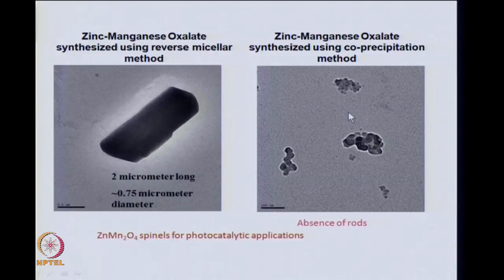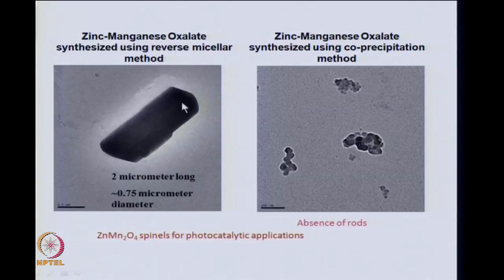On the right side, we have used the same conditions for making the same compound using the co-precipitation method, where we do not have any surfactants or microemulsion. And as you see, this microemulsion process containing a cationic surfactant gives a nanorod kind of morphology, whereas in this case, where we have not used any surfactants or microemulsions, you can see that there are no rods or anisotropic structures. They are more or less spherical agglomerated particles of zinc manganese oxalate. If you take the X-ray diffraction of both of them, they will have the same X-ray diffraction, telling you that in both cases the product is the same. However, the morphology is very much dependent on the methodology by which you have obtained them.